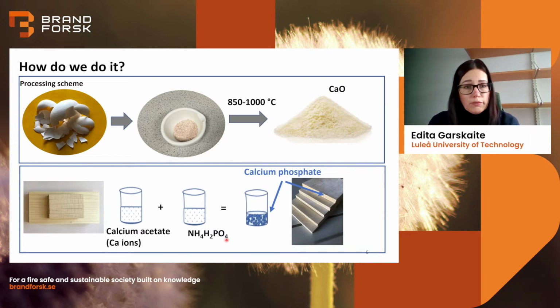Then we take another solution, of ammonium dihydrogen phosphate. This time we chose this material because it is by itself a fire retardant. And when you mix these two solutions, you get calcium phosphates, different calcium phosphates. So wood is first treated with one solution, then treated with the other solution, and then we hope to obtain these different calcium phosphates within the wood matrix, the same as in a solution without wood.